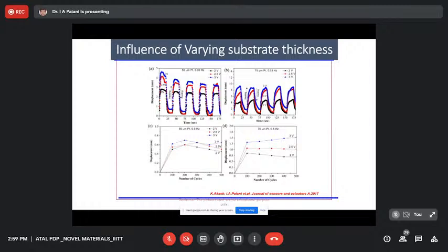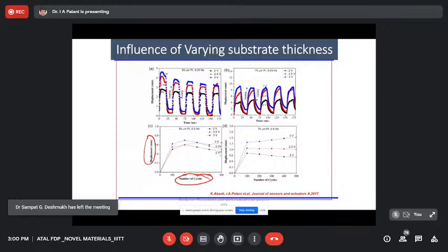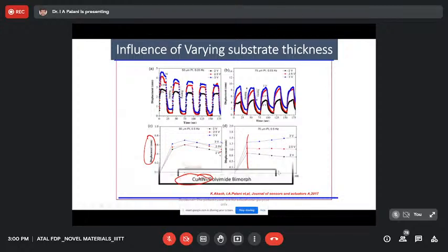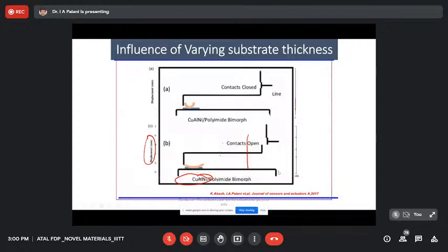Which was completely interesting, and completely encouraging. Okay, so this is a kind of characteristic which we have studied with respect to displacement and number of cycles, and we have varied the voltage, and we have used 2 different samples, one with 50 micrometer and another with 75 micrometer. With 50 micrometer we could see the overall life cycle behavior, and at 75 micrometer we could see beyond 500 cycles there is not much variation observed. So basically we could go up to 1 lakh cycles.